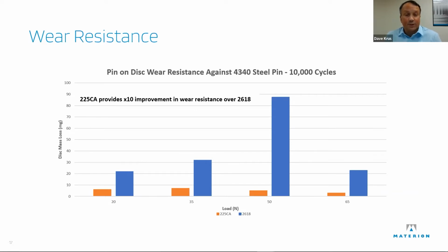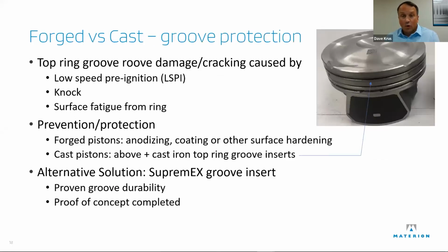But again, this is the wear resistance that's provided by those silicon carbide particles that sit on the surface and hold against the weight. They're very low in friction as well. So now thinking about that, and remember we said that the groove wasn't protected in a Supremex. You don't need to protect the groove. Well, in forged or cast pistons, because that piston we replaced was cast, and some of the two-stroke pistons are cast hypereutectics, do you need to protect the groove in those?